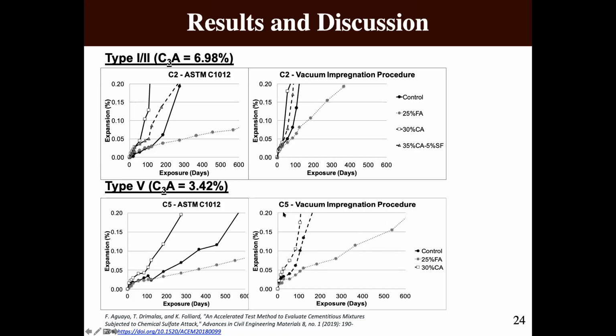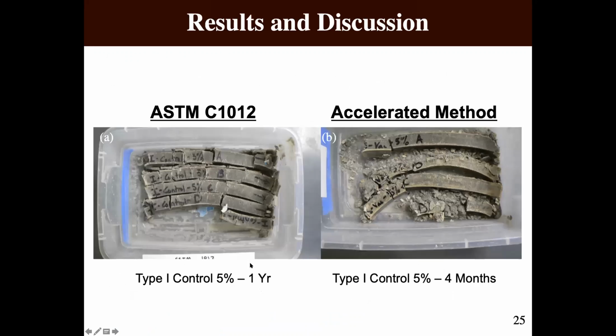In fact, you have a Type V that has a 25% fly ash addition, and at about a year is when that fly ash actually exceeded that 0.1 expansion, right? So again, while it's still a fairly lengthy time, it is much quicker than the typical traditional 1012 method here, 600 days of testing and still not exceeded that expansion.